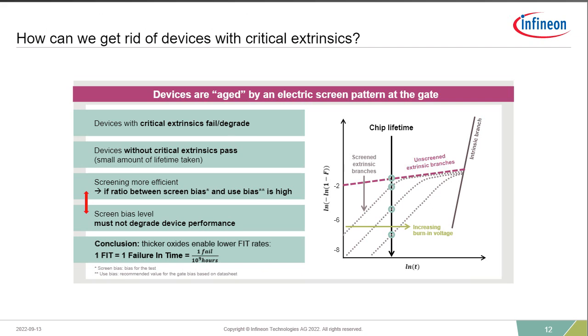So, taking a look at this Weibull curve again. The x-axis here is the time to failure, and the y-axis is the rate of failure. One of the ways you can improve reliability is to drive the gate harder and increase the voltage on the device, for instance the burn-in voltage, and you begin to move further to the intrinsic branch of the curve. So instead of driving at 15 volts to validate a device, you hit it with 30 volts. That pushes you further down in terms of rates of failure, and further to the right in terms of the reliability or long-term rate of failure of the device.